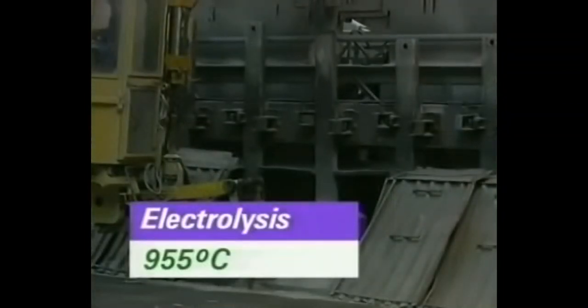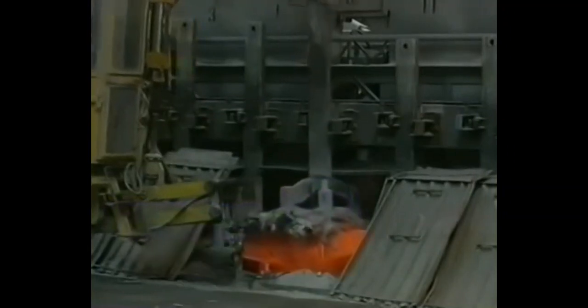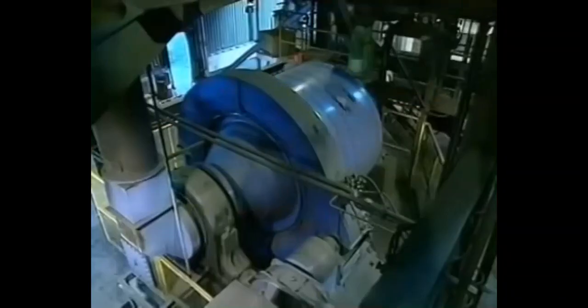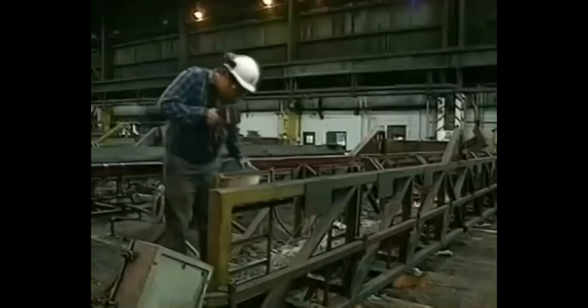The electrolyte is at about 955 degrees Celsius. At this temperature, the carbon anodes gradually burn away in the oxygen from the electrolysis. Eventually, the anodes have to be replaced, and this happens every 28 days or so. The remaining carbon is broken off the old anodes, crushed, mixed with new coke and pitch, and pressed into shape. The newly pressed anodes bake for about 24 hours in gas-heated pits. This produces electrodes which will conduct electricity and not crumble away in the cells. The temperature of the pit is important and is checked on a regular basis.